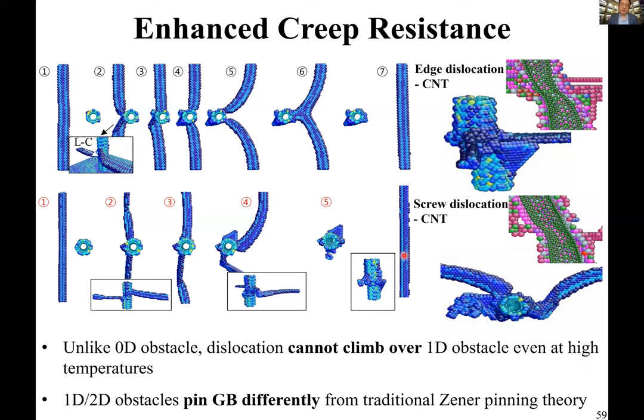But with micron length carbon nanotubes, the dislocation can't easily climb over it. You actually have to use a brute force all-around looping to be able to move a glissile dislocation across a carbon nanotube. And unlike a forest dislocation, it doesn't react with a glissile dislocation. This also refined the grain because, unlike particles which pin the grain boundaries by the Zener pinning theory, the 1D particles with the same volume fraction pin the grain boundary more effectively as well.